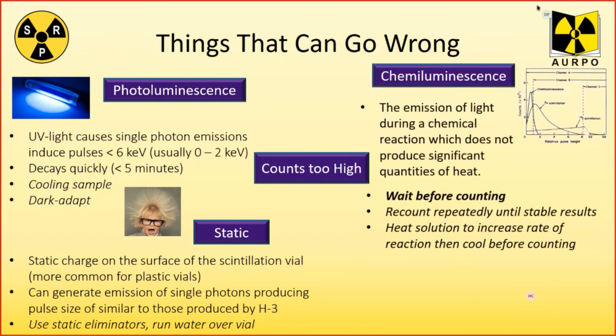And finally, counts could be too high due to chemiluminescence, which is the emission of light caused by a chemical reaction. Ideally, to remove chemiluminescence, you'll just wait for the reaction to terminate before counting. Alternatively, you can count repeatedly until the sample gives stable results. The reactions causing chemiluminescence can also be sped up by heating the solution, but you do have to be aware of any additional safety concerns from doing this, and the sample does need to be cooled before counting as well.